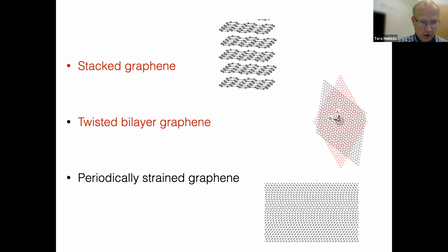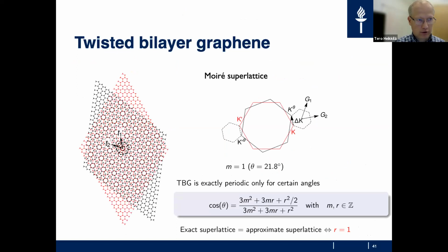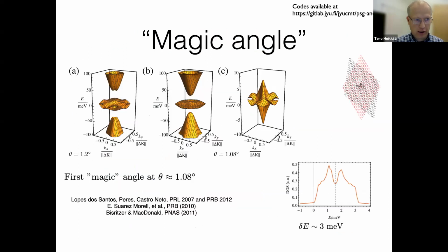Okay, I'll try to spend a few minutes on twisted bilayer graphene. The idea is basically that you take two graphene layers, stack them on top of each other, and then twist them with respect to each other, and you get this moiré superlattice. Let me cut the details a bit. Basically, at a certain magic angle of twisting, you get a flat band. And this flat band was known already for more than 10 years.